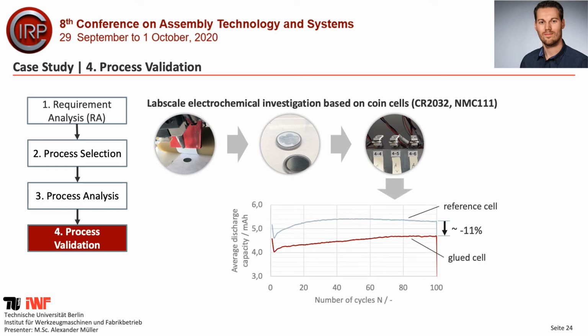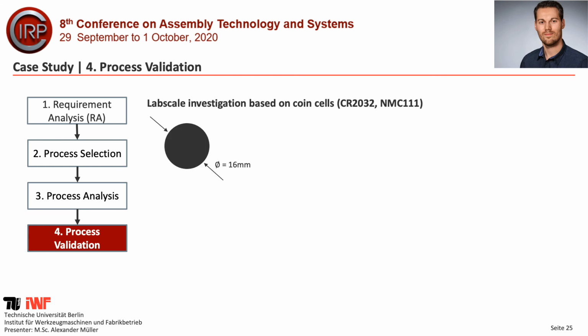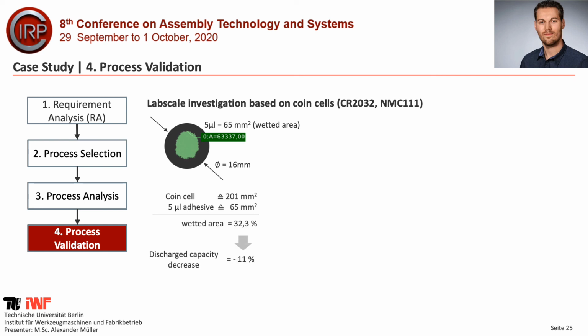So we glued some cells and built some coin cells with them and compared them with a non-glued one. Then we charged and discharged them 100 times and compared the discharge capacity. You see a difference of about 11%. But what does it exactly mean? If you build a coin cell, you use a diameter of 16 millimeters, you add, in our case, a 5 microliter spot of glue, roll over, and you produce a 65 square millimeter wetted area. This means we have a wetted area of 32%. And this is a discharge capacity decrease of 11%.